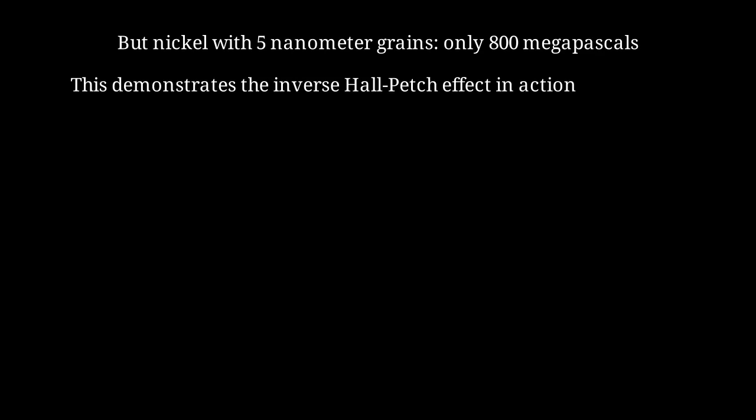However, when grain size is reduced further to just 5 nanometers, the strength drops to only 800 megapascals. This clearly demonstrates the inverse Hall-Petch effect. Making grains too small actually reduces strength.